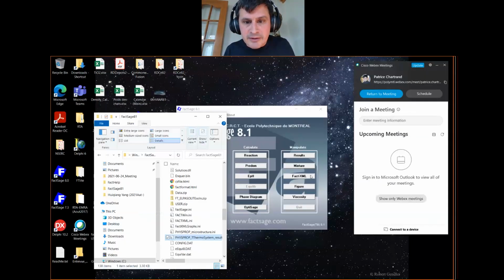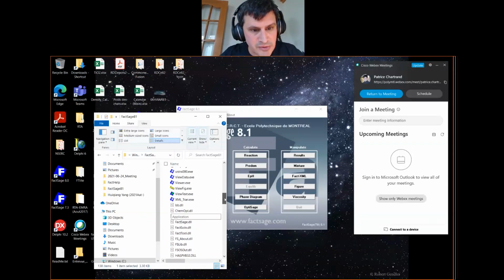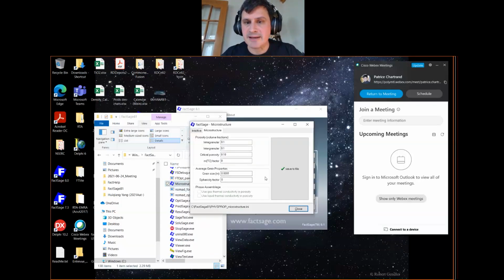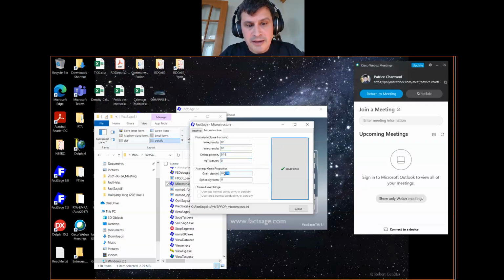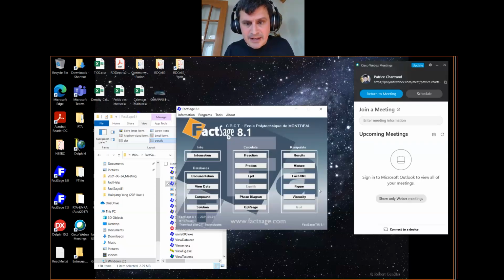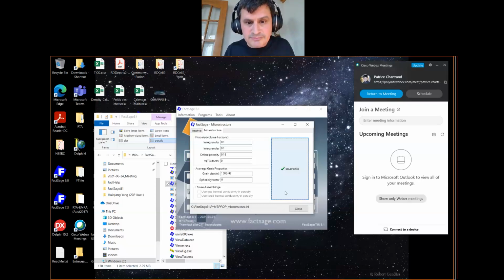But before going to the equilibrium module, I must go to the microstructure module to fix the microstructure characteristics. So the intragranular porosity would be 10%, intergranular 10%, 18% critical porosity, M equals 0, and grain size will be 100 E minus 6 meters. And I will save this. Now you can go in the equilibrium module,